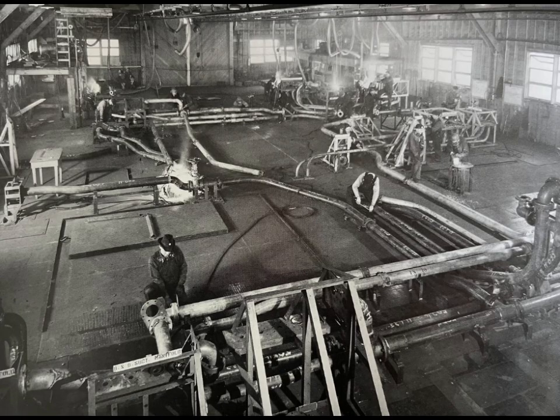These failures stemmed from multiple causes. Steel metallurgy with ductile to brittle transition temperatures too high, stress concentration at welded corners where rectangular openings created weak points, welding defects where improper technique left internal voids or inclusions, design flaws where load paths weren't properly considered. But they all shared one commonality. They happened in welded ships, built rapidly under wartime pressure by workers who'd learned their trade in weeks rather than years. The investigation following the Schenectady failure revealed uncomfortable truths.